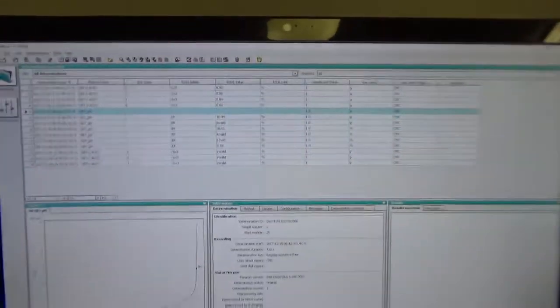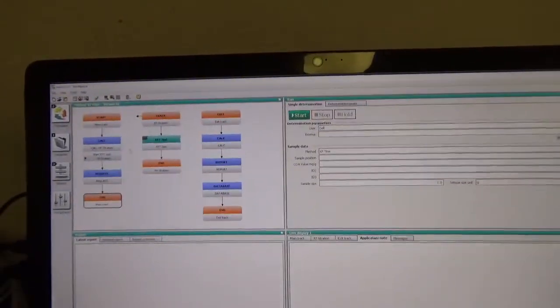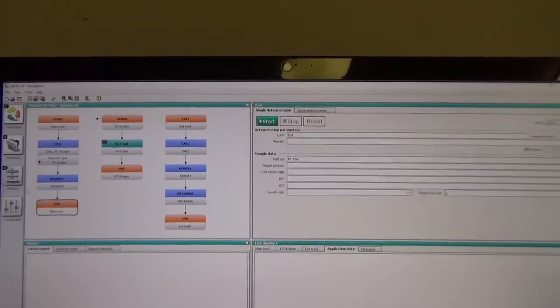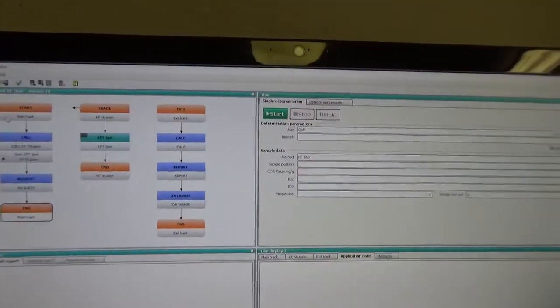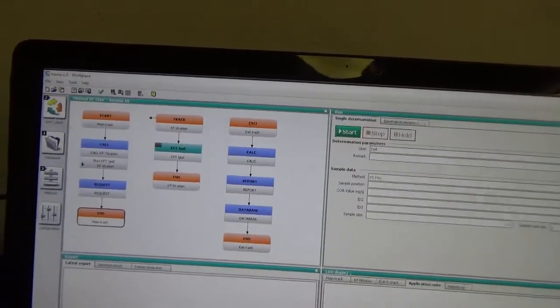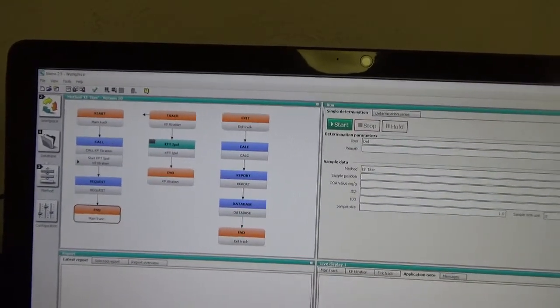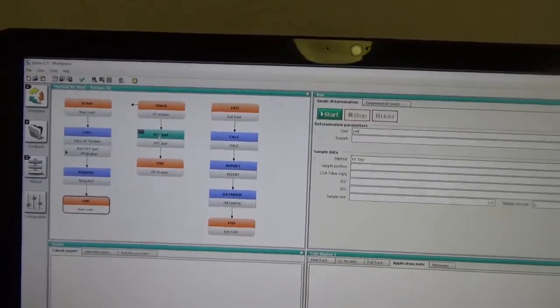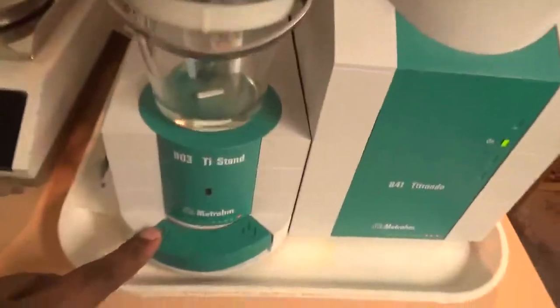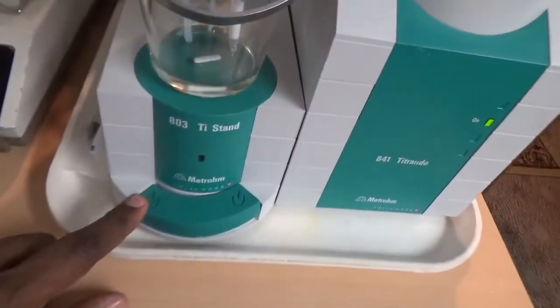848 Titrino Plus. Now to do the Karl Fischer titration, we use the Tiamo, as I said. And in the Tiamo, first we make sure that the Titrando is doing the conditioning part. So we get the method first, the Karl Fischer titer, the method that we are using to do the conditioning part first. So basically what it is doing in the conditioning time is, you basically take the ethanol solution by pressing this pump,